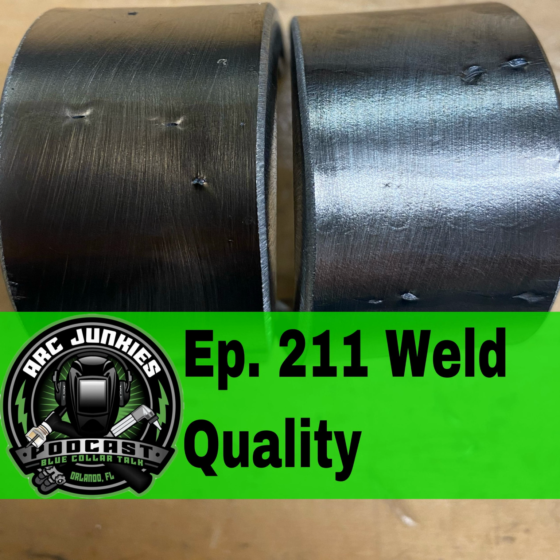Any amount of overlap is an automatic defect. At that point, we're going to have to cut that weld back out and redo it. What's going to happen is we create almost an acute angle between the overlap and the base metal. On anything that's holding up a lot of weight, or has an excessive amount of vibration, or is a cyclically loaded weld, that's going to start to propagate a crack underneath that overlap surface. So we want to try to avoid that. That's a sharp corner. We want nice, smooth transitions between the weld and the base metal anytime we can.